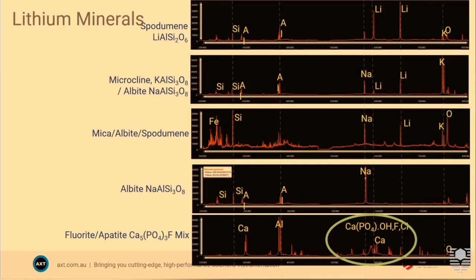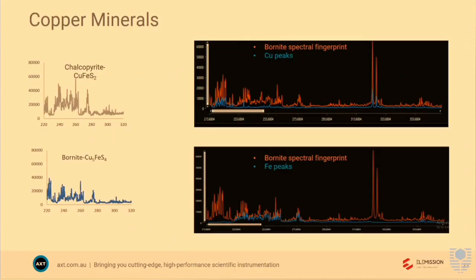So LIBS has never been classically used for quantitative chemistry because of those matrix effects. So you need a matrix match calibration. But in today's world of chemometrics, you can build up a huge chemometric calibration where you, instead of having like 3 or 10 standards, you can have 100 or 1,000 standards for this multivariate chemometric calibration. So high lithium, high iron, high lithium, low iron. So it's the right time for this type of technology because you've got all the hardware and processes around there. So classic lithium spectra. This is copper minerals. So you can see the copper peaks in blue, the iron peaks in blue.